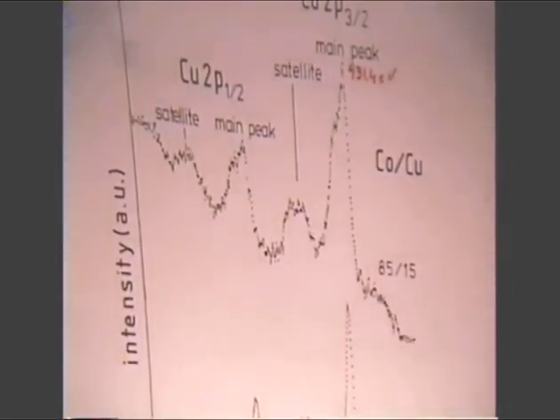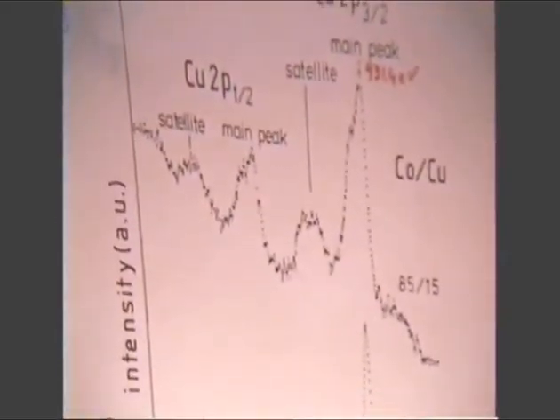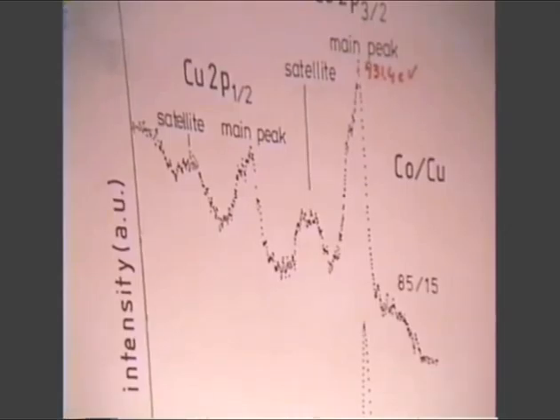Well, now I will show you the XPS results for copper. These are the copper XPS spectra for the nitrate-calcined catalyst. And I recall to you that for copper 2+ compounds, the copper 2p3/2 transition is characterized by a main peak and by a satellite peak at a higher binding energy. And copper 1+ compounds don't have a satellite peak. So it's rather easy to check the presence of copper 2+ ions and copper 1+ ions in the XPS spectra.